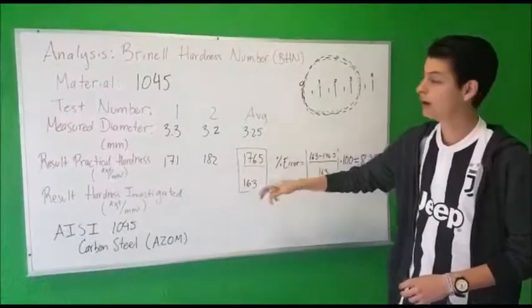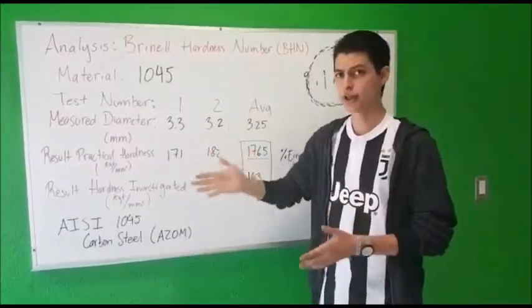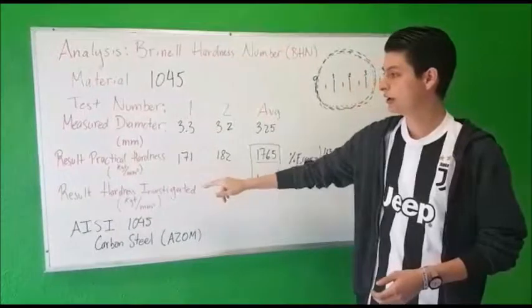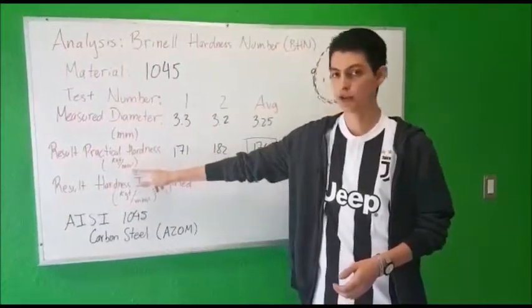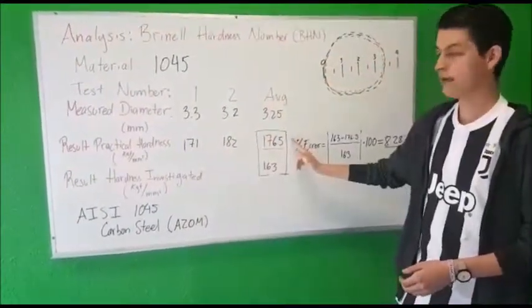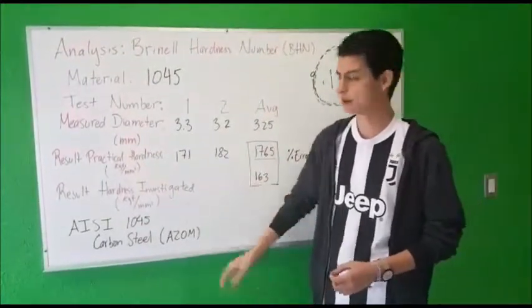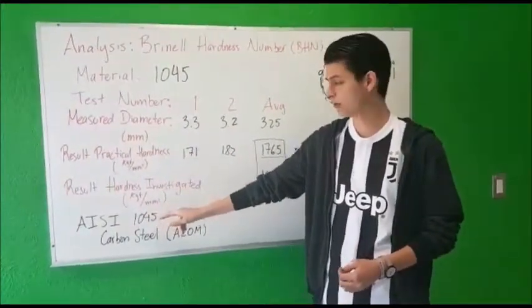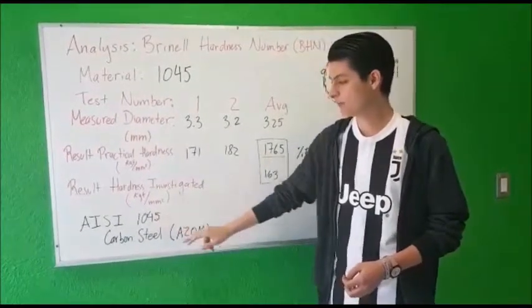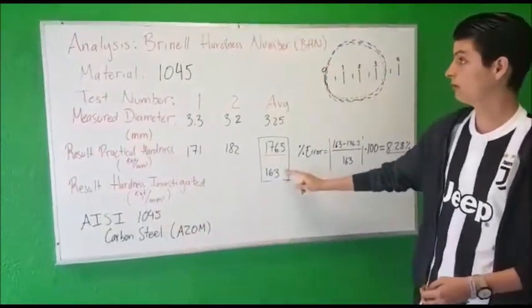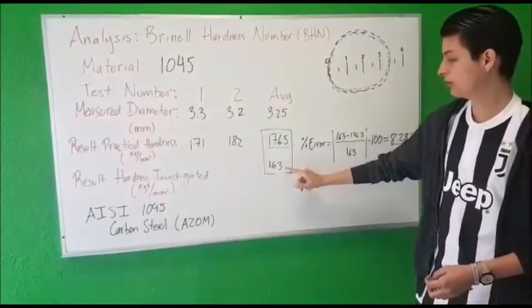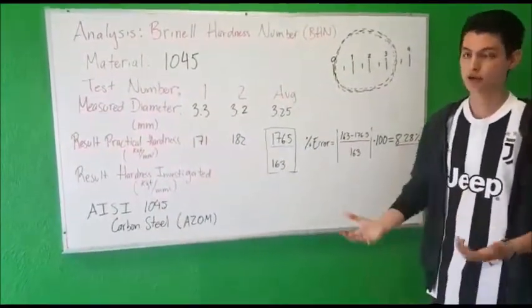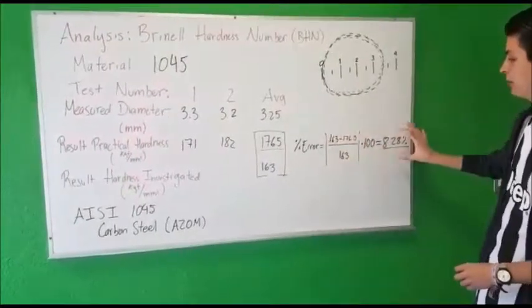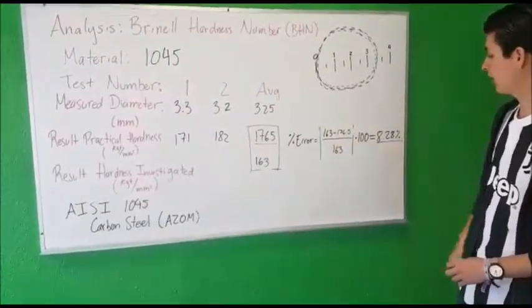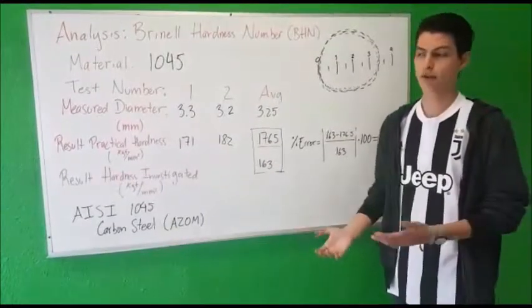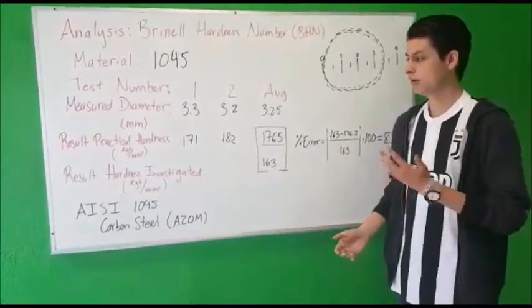We got an average of that, and then we searched in the tables for the Brinell hardness number in kilogram force over square millimeter, and we got this average. Then we investigated in the American Iron and Steel Institute for the 1045 Brinell hardness number, and we got 163. We got a percentage of error of 8.28, which is pretty close, given that it's lower than the 10% that is normally accepted.